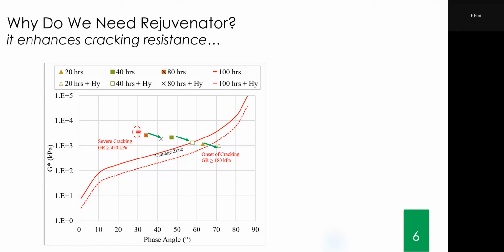So these are the ones with the rejuvenator. We added this rejuvenator, and each one of these points just jumps back. The triangle here jumps back below the dash line. The rectangle jumps back here, the cross, and so forth. But you can see the one with 100 hours, it didn't even care. It didn't even move.